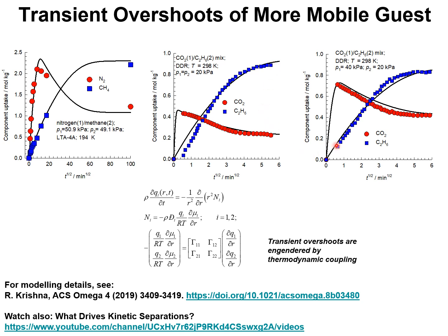Here is experimental data for the same mixture — CO2 and ethane in DDR zeolite — but with different partial pressures: CO2 at 40 kilopascal and ethane at 20 kilopascal. Again, we see a pronounced overshoot in the loading of CO2 during the initial stages of the transient uptake.